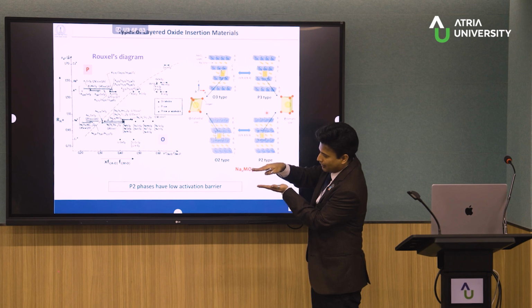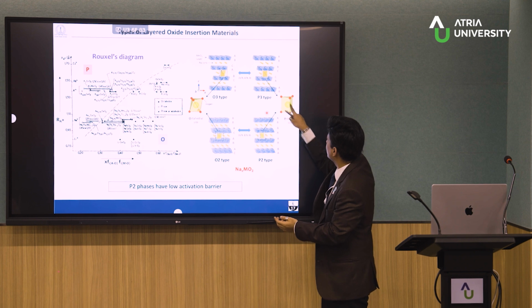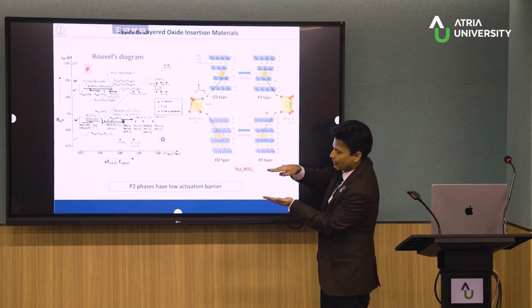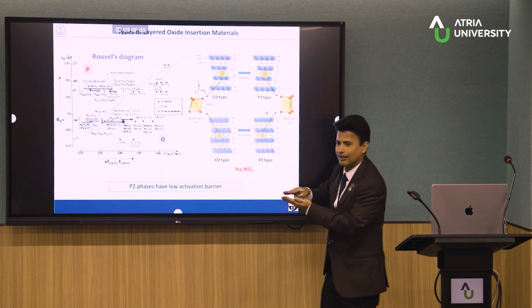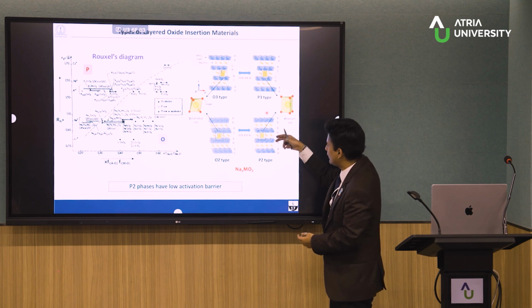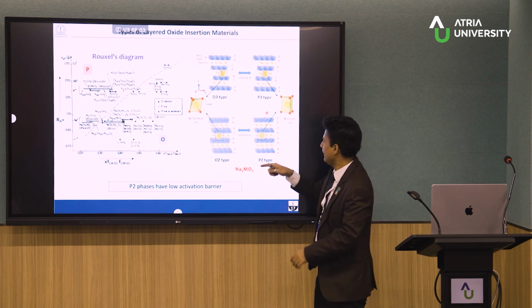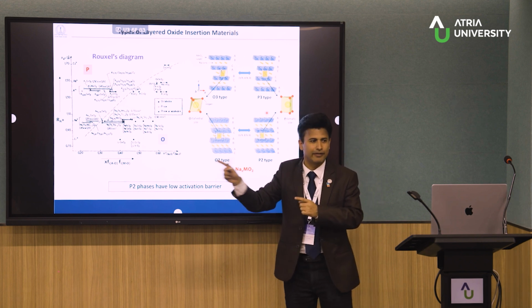Because of that, the interlayer distance is low. In case of prismatic, they are exactly on the top of each other, 3 oxygen, 3 oxygen. Oxygen repulsion is very high. That's why the interlayer distance is slightly higher. When this distance is slightly higher, more opening, then the sodium can move in and out very, very fast.